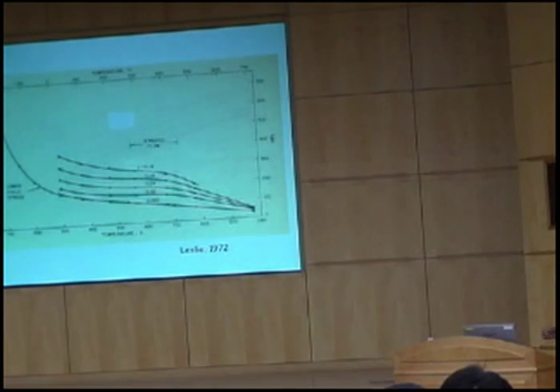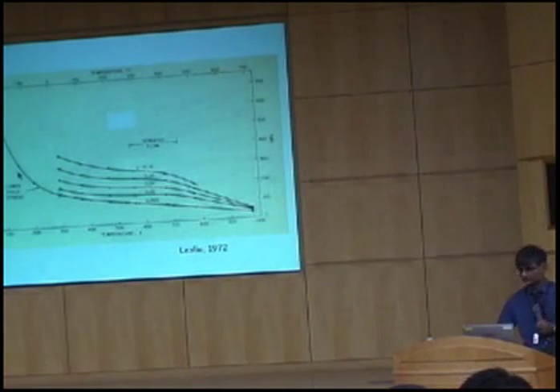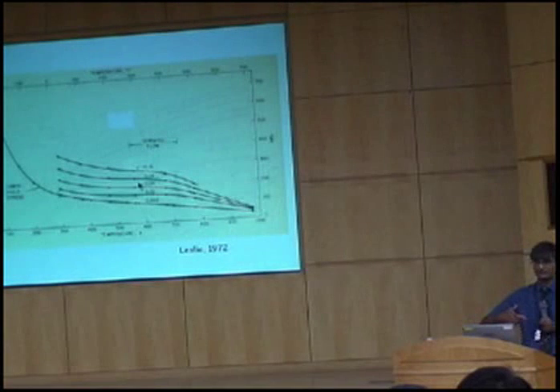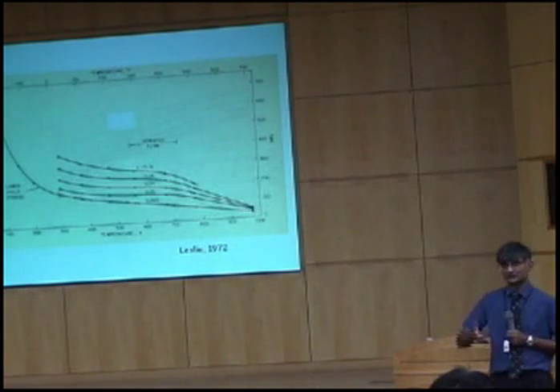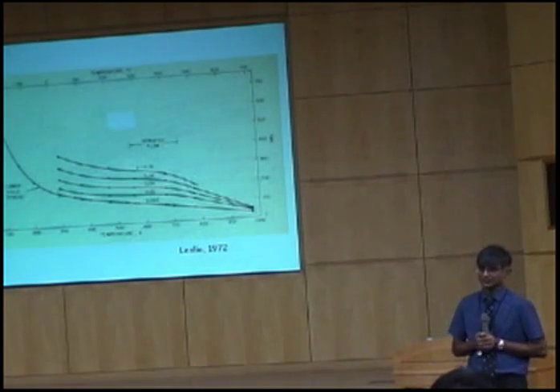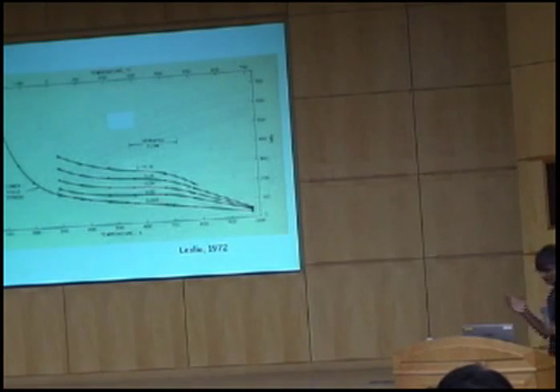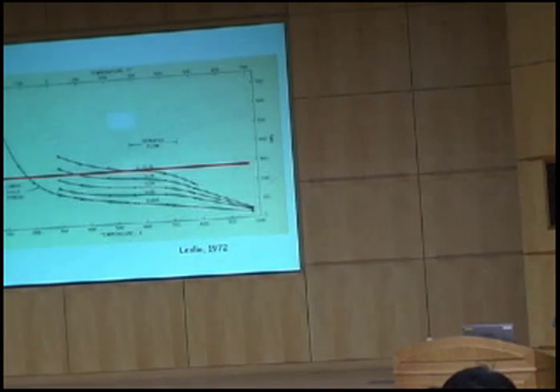This is how the strength of iron varies as a function of temperature. So let's imagine that we are looking at this particular level of strain. Then it's very, very sensitive to temperature as we go down to low temperatures. And of course, if you vary the strain rate, then the strength increases with strain rate. So this is a basic feature of body-centered cubic iron, that its flow stress, the stress required to move dislocations, is very sensitive to temperature at low temperatures. And this has a very big effect on properties, because this is the stress required to move dislocations, and this is the stress required to cleave the crystal. That means to break it without much plastic deformation.